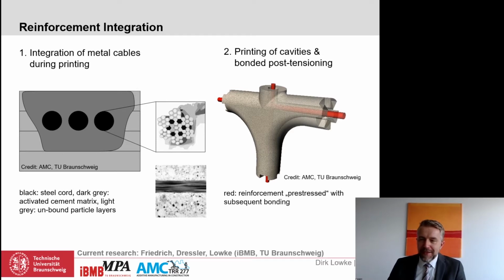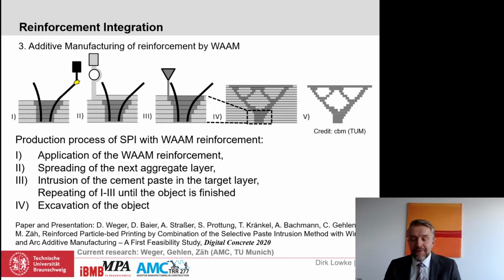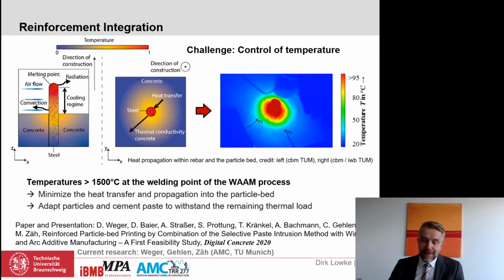But a third very interesting strategy is the simultaneous manufacturing of steel reinforcement by wire and arc additive manufacturing. This strategy is pursued for the selective paste intrusion method at the Technical University of Munich, also within the framework of the Collaborative Research Center TRR 277. In this process, the reinforcement is built up section by section before the printing of a concrete layer. The main problem, however, is the heat generated during the welding process.